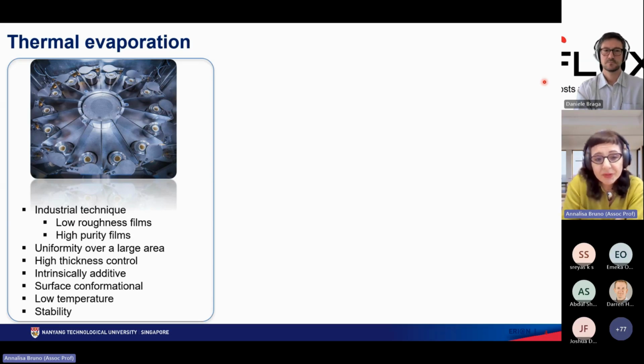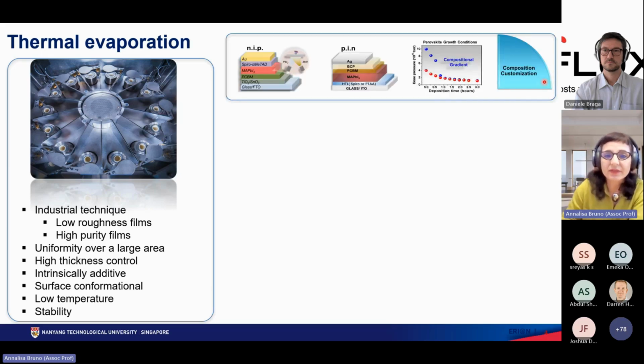So it's a mature industrial technique that can guarantee low roughness films with high purity, which comes intrinsically from the sublimation process. It can guarantee good uniformity over a large area and high thickness control, so we can go very large but also very thin. It can be intrinsically additive, so that means that we can build up multilayer structures. It's surface conformal, can go on different substrates, but it is also an intrinsically low temperature process, and it can also guarantee stability. And we will see how specifically.